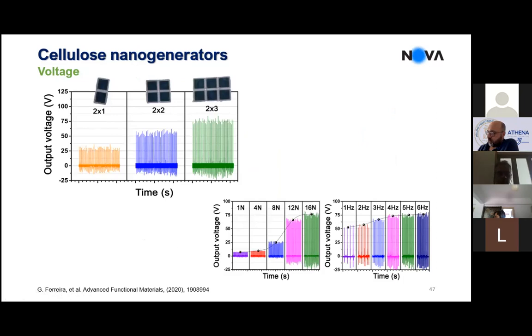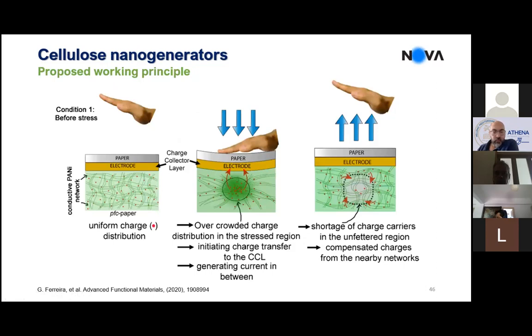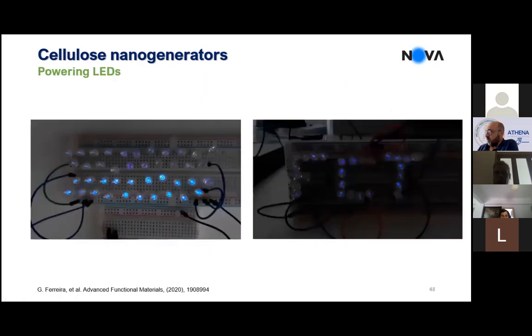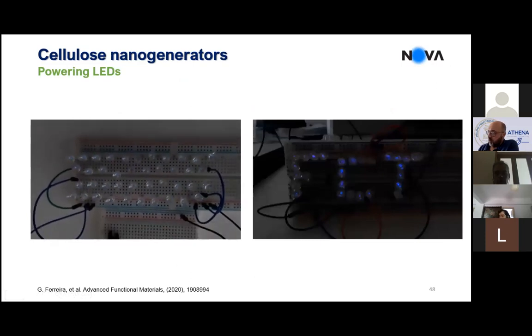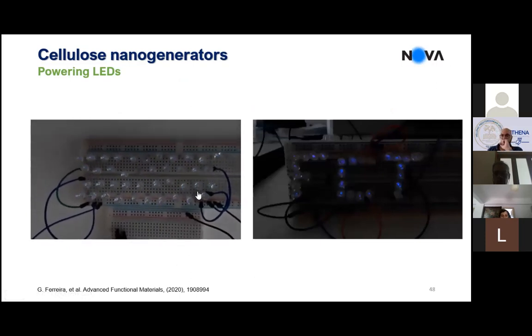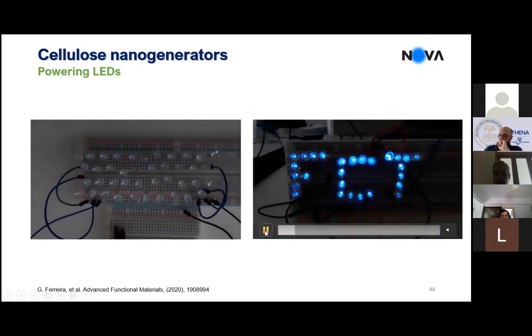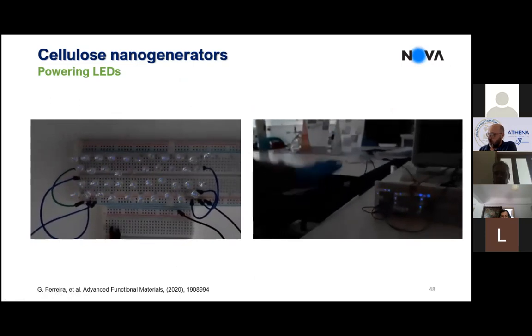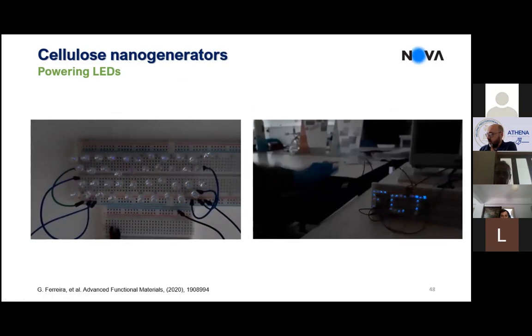And we made a study. I don't have this slide here; I removed it just to keep it simple. But we also made a study on the type of electrode that is better to promote this charge transfer, because of course the Fermi level of the electrode material will be important to maximize this charge transfer mechanism. And of course, this is just an example on one of these cards. By punching it, you can light up, in this case, 29 LEDs. These are just the letters of the acronym of our university. And you see, just by punching these cards, how you can transform mechanical energy into electrical energy.